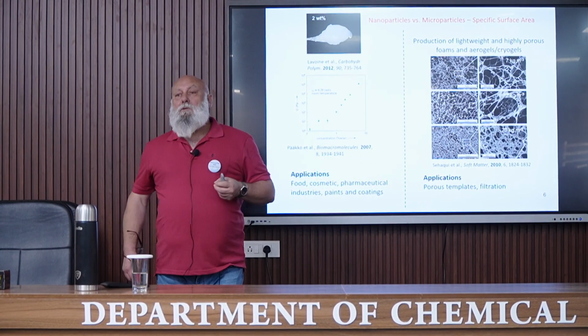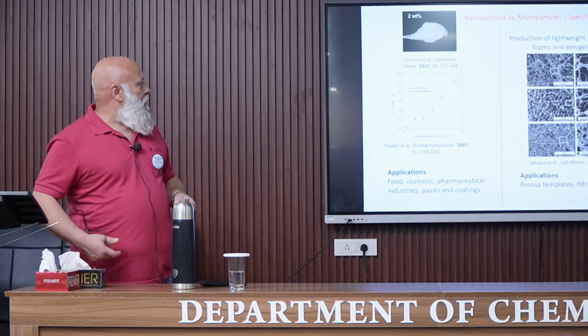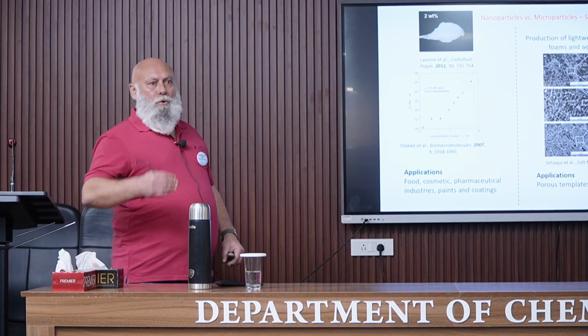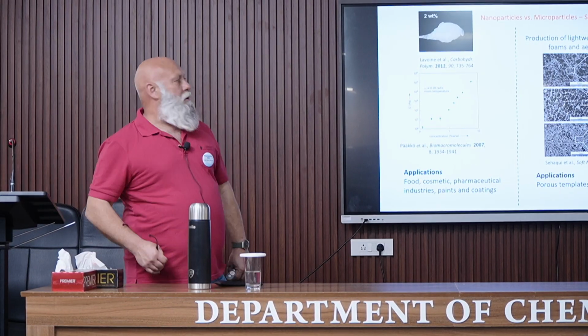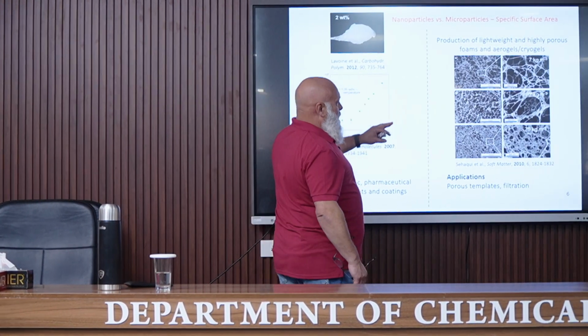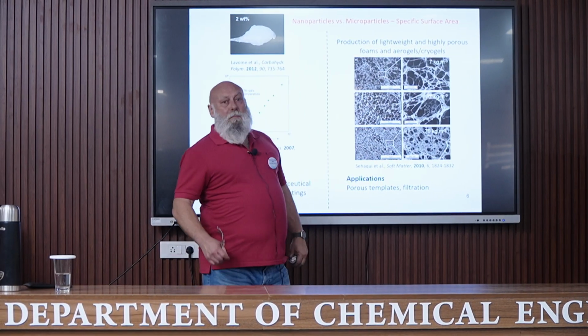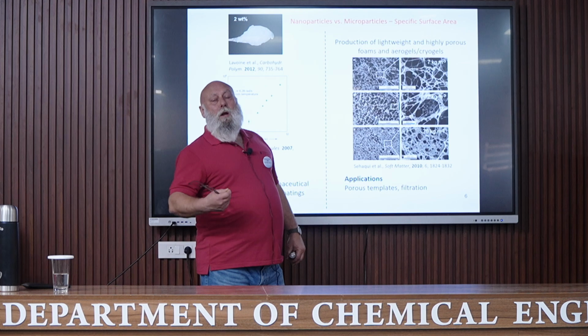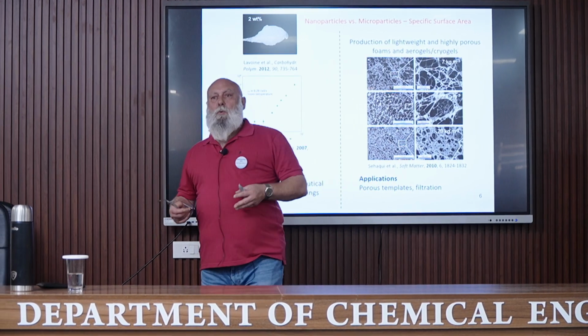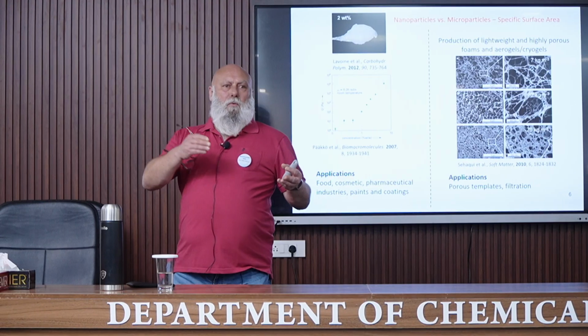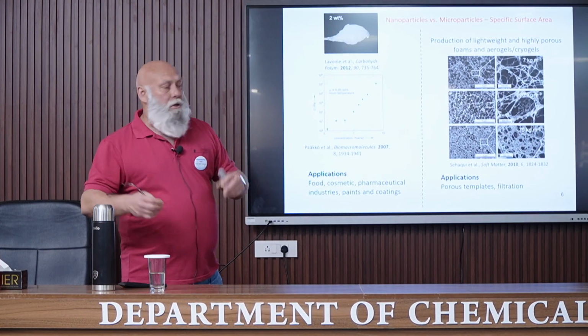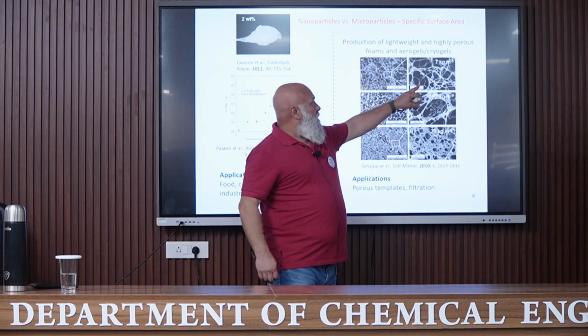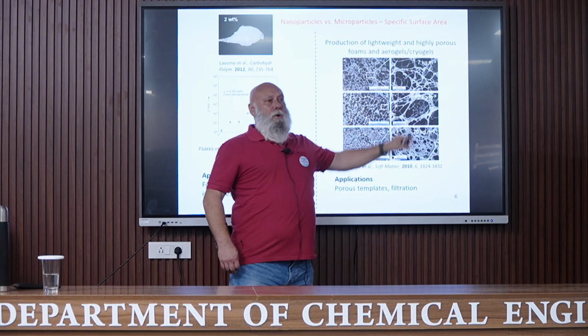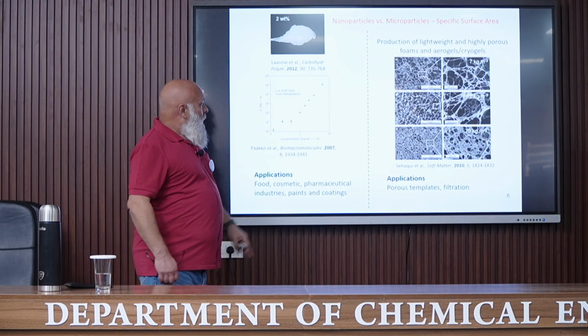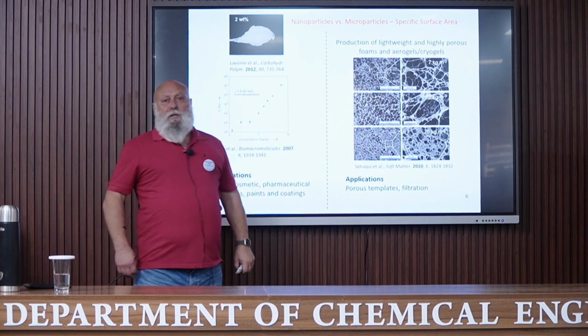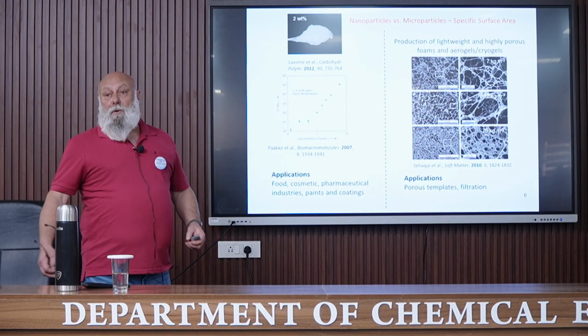In fact, the aqueous dispersion of cellulose nanofibers, for example, can be freeze-dried to remove water without collapsing the nanofibrils. And so we obtain this kind of cryogel that can have a very low density. In fact, it depends on the liquid medium. If it's water, it can be a mixture of water and acetone and so on. It changes the porosity. But you can see that in some cases, the density is very low, 7 kilograms per cubic meter. And of course, it can lead to applications for porous templates, but also for filtration.